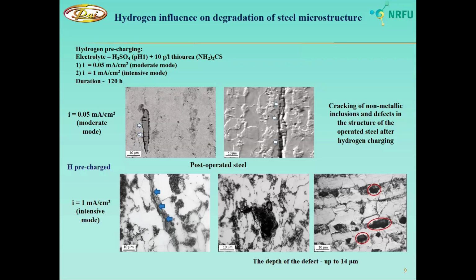So analyzing microstructure after hydrogen charging, we can see a cracking of non-metallic inclusions for the operated steel, and also all non-metallic inclusions have at least a partial loss of cohesion with the matrix. And after intensive mode of hydrogen charging, also cracking along the boundaries between non-metallic inclusions and the matrix was observed, and complete decohesion of non-metallic inclusions from the matrix formed defects in the steel.